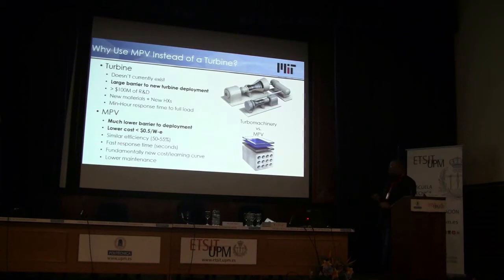So I didn't really talk about this. I'm not going to go back, but one of the things about the way we have the system arranged, you have these pipes that the silicon or the fluid is going to flow through. And we have this cavity, and the PV can essentially be dropped into the light, and it can be actuated in or out of the light. And so by doing that, we can actually ramp from full on to full off as quickly as you can actuate it, which is on the order of seconds. And that's actually, from talking with grid operators, a really, really attractive feature of doing it this way.